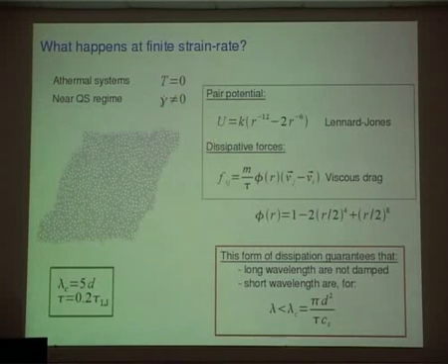The problem is that when you shear a system, when you deform a system, you are working on your system, so you're injecting energy in the system, and if you want the temperature to remain 0, you must find a way to extract the energy. There are various ways to do this. There is one way which is in fact correct, and which is essential. So we do this by introducing essentially dissipative forces. So on each pair of particles, we'll just introduce a viscous drag force.